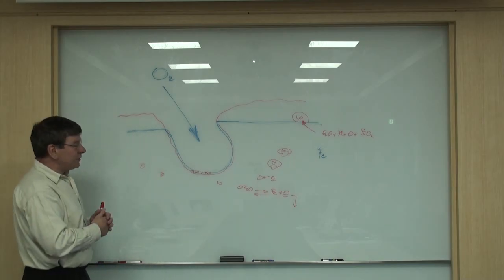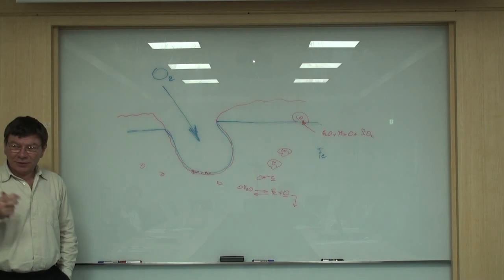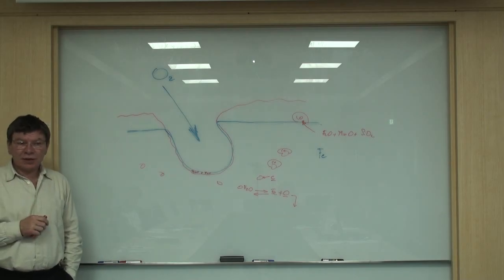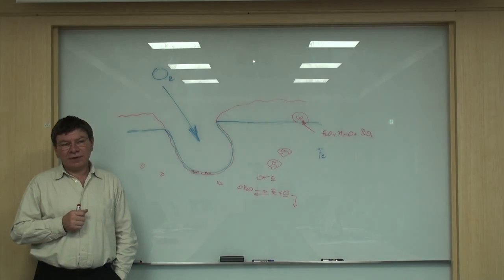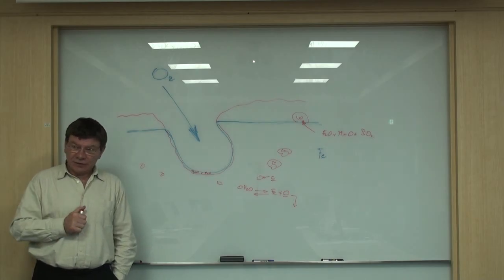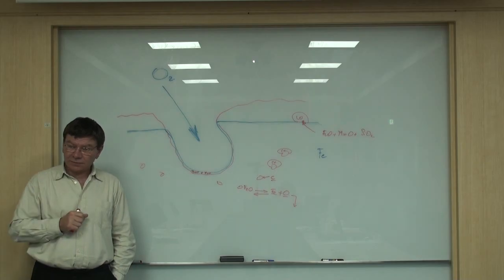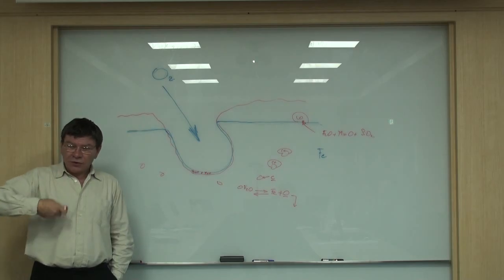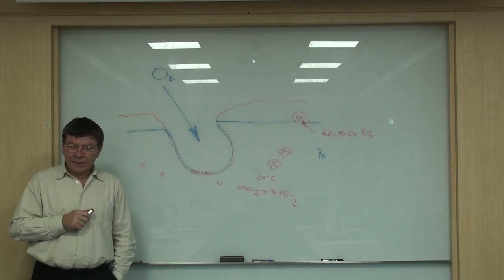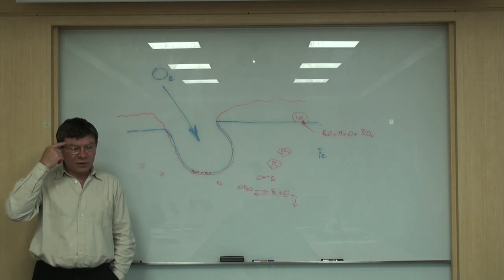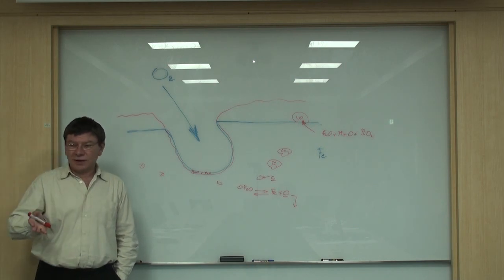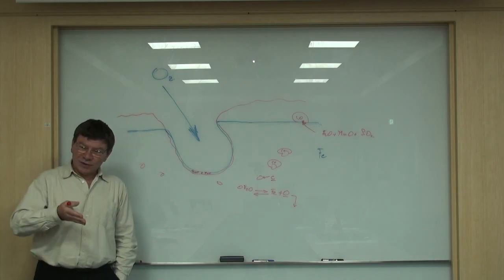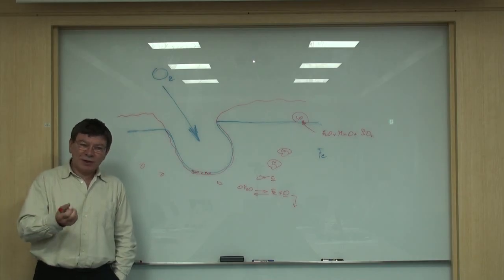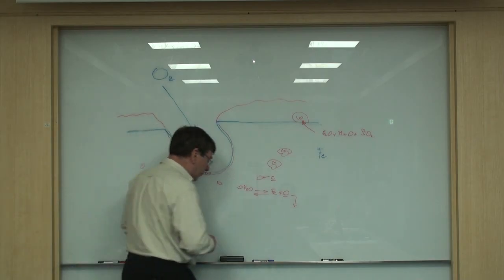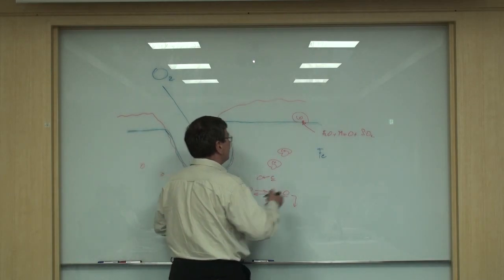But we are intelligent now since 30 years, and we know the foaming slag practice, because at the origin it was the Japanese who had invented the oxygen injection in the furnace, because the current was very high. So the electrical energy was very high, and they had the idea to inject oxygen to fasten the melting practice. But they have seen that the yield is going down. So they say, okay, if the oxygen is oxidizing the Fe, the cheapest way to reduce the Fe, because scrap is costing money, is to inject carbon. So they start injecting carbon, and they have seen that the slag is foaming.